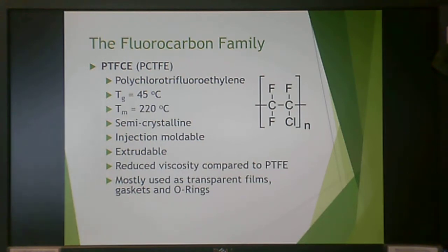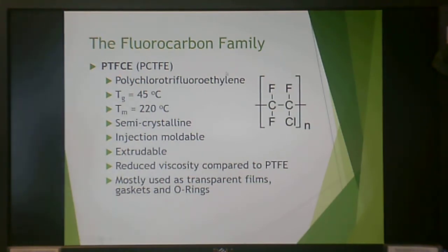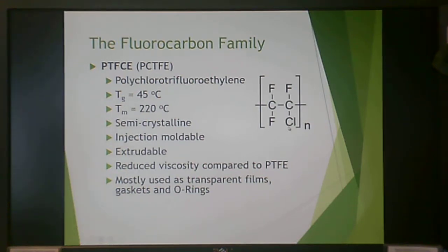Starting with the non-Teflon members: PCTFE, or polychlorotrifluoroethylene, has a TG of 45°C and a TM of 220°C. Its repeat unit has one chlorine and three fluorines — hence trifluorochloroethylene. It is a semi-crystalline material, injection moldable and extrudable, with reduced viscosity compared to PTFE. It is mostly used in films, gaskets, and O-rings.